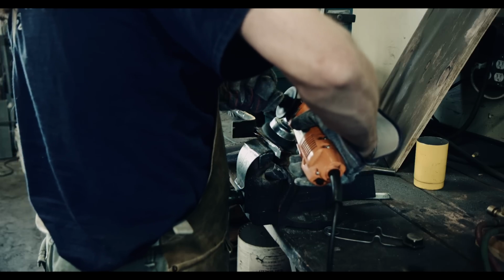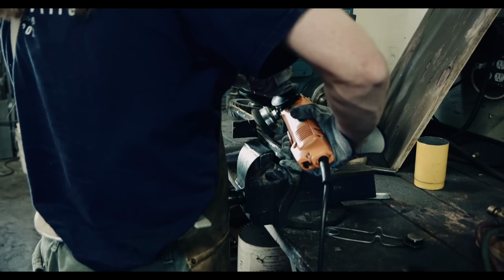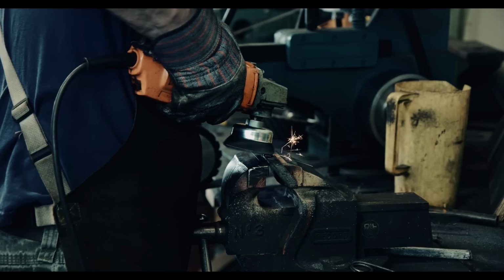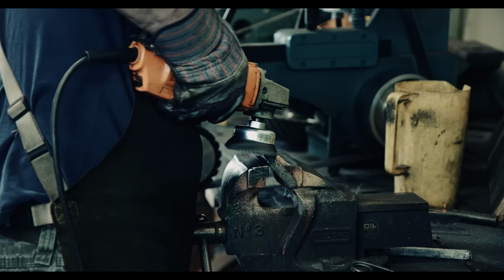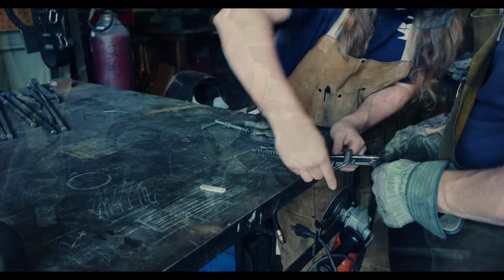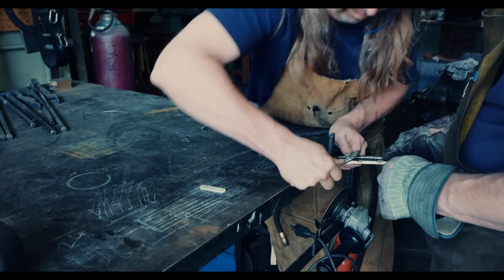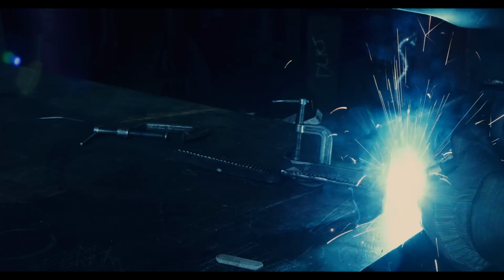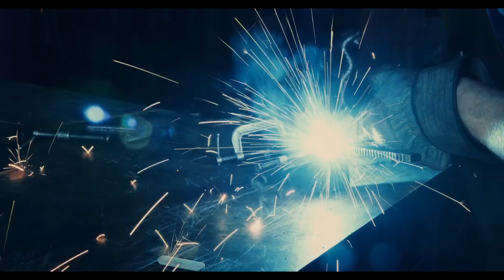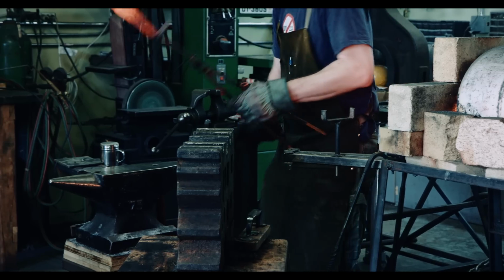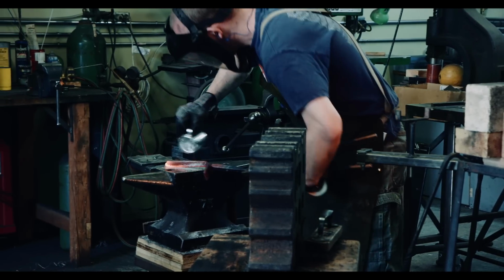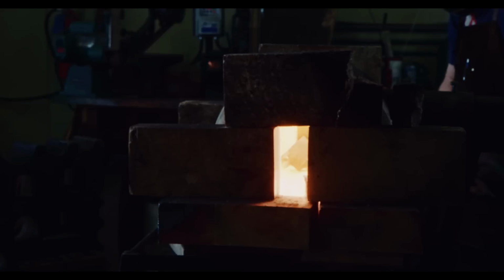Before I can forge weld the wrought iron teeth to the outer part of the spearhead, any scale that is built up needs to be removed again. A couple quick tack welds hold the wrought iron in place but will not form inclusions in the finished product. Now it's back into the forge where I bring everything up to welding heat.